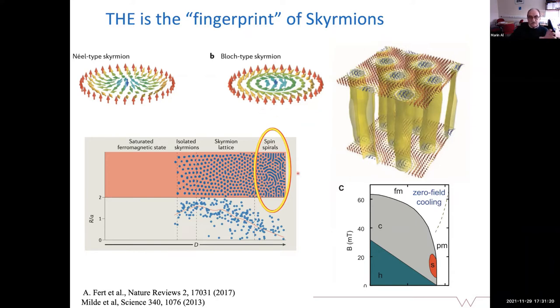Across, let's say, a skyrmionic phase crystal, that always occurs under a little bit of magnetic field, and is very close to a phase transition. So in other words, the magnetization must be soft to start whirling in this very particular way. So either it's a Neel type skyrmion or a Bloch type skyrmion, you see the way of winding is different.